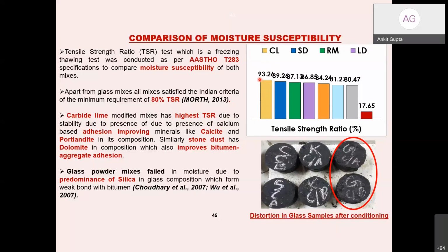If you see all the values, they are more than 80%, like 80.47, 81, 84, 86, 87, 89, 93. Only for one mix the value is lower than 80%, and that is the glass powder mix. So the glass powder mixes are failing in moisture, as I discussed in the previous slides, because of the predominance of silica. Silica is responsible for the failure in moisture, making a weak bond with the bitumen, which breaks in the presence of moisture.